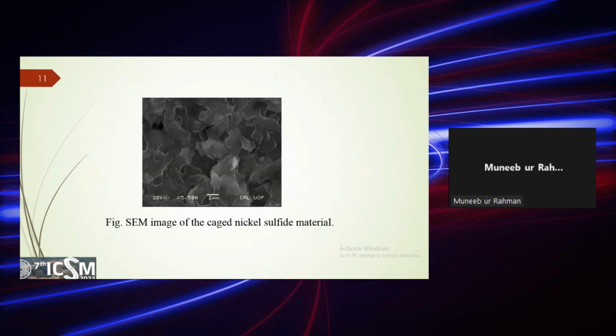This is the surface of the material, which plays a very crucial role in the humidity sensing process. This is the same image of the cage nickel sulfide material, and we see here flakes of the material are formed on the surface, and there are also pores and pore channels available on the surface of the material, and one can see these pores and pore channels in the material, and also the flat surfaces of the flakes on the surface of this material.